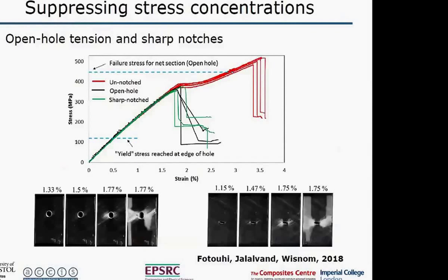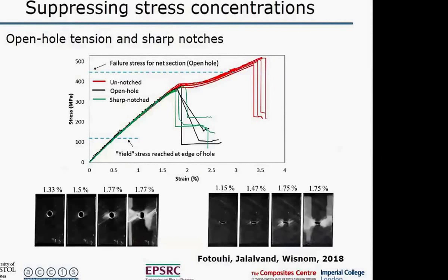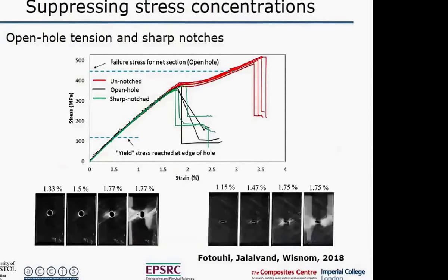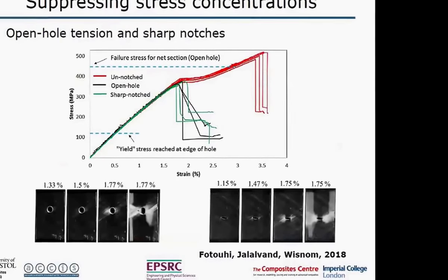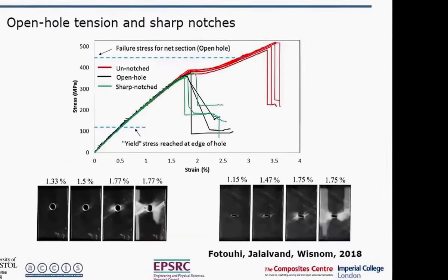So this pseudo-yield stress is reached quite early on, then we get a gradual increase in fragmentation around the notch. And on these plots here, what we're actually seeing really is the delamination associated with that. Even at this strain here, there's quite a bit of fragmentation, which you can't see so much. But it's gradually increasing until you get a pseudo-yielding across the whole of the cross-section, at which point you get the load drop. So this was pleasing. This was the whole premise of the program, that by introducing the pseudo-ductility, we could reduce the effective stress concentrations, and it seems to work very well.